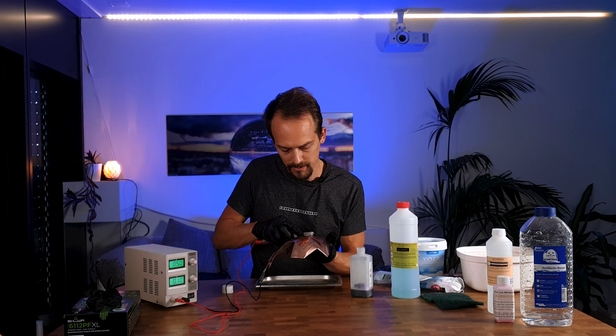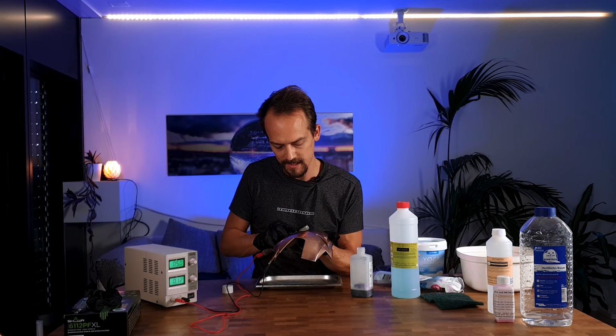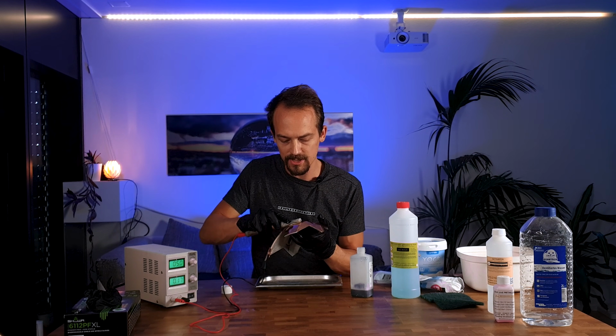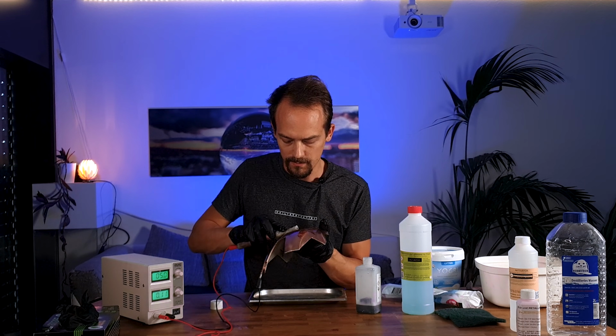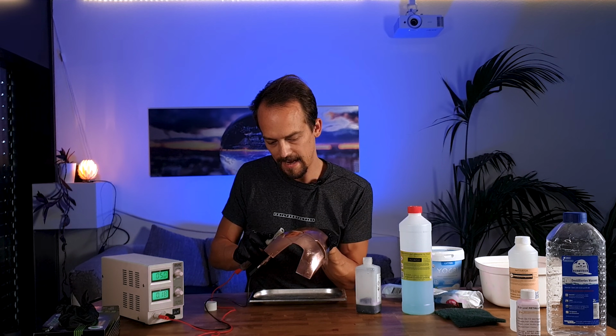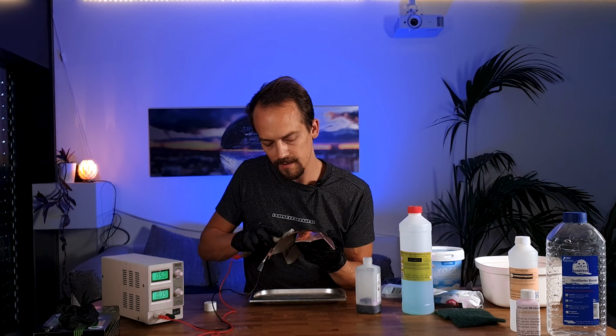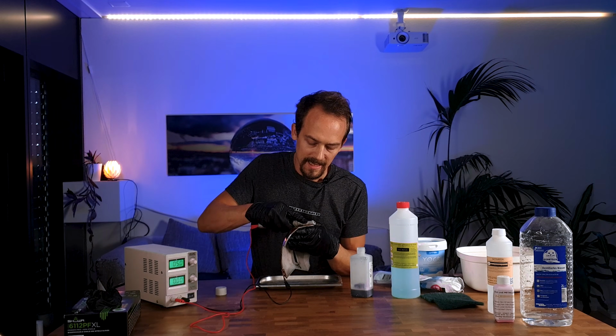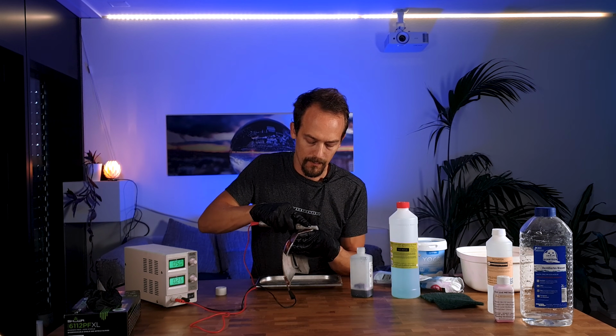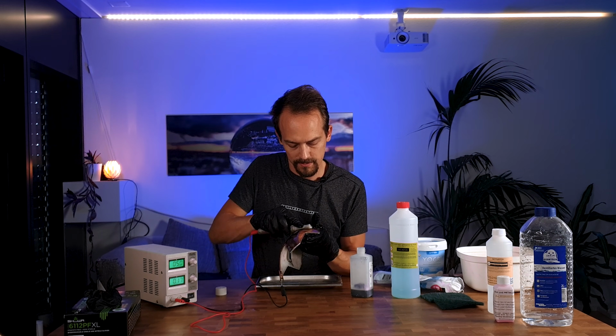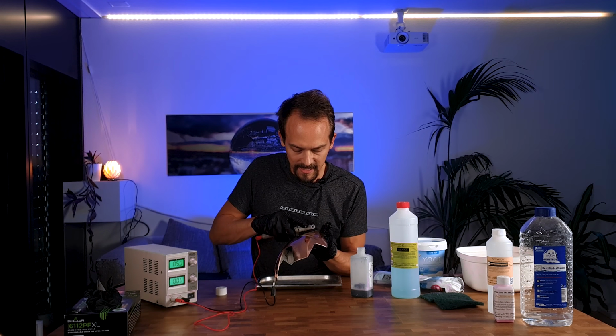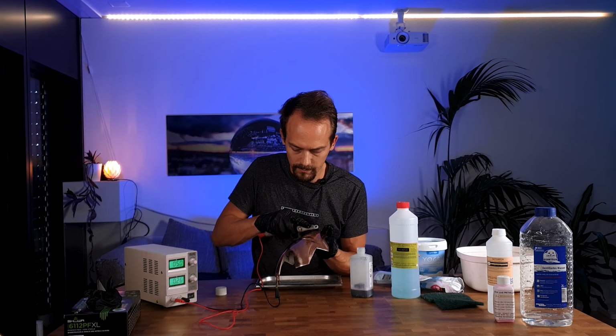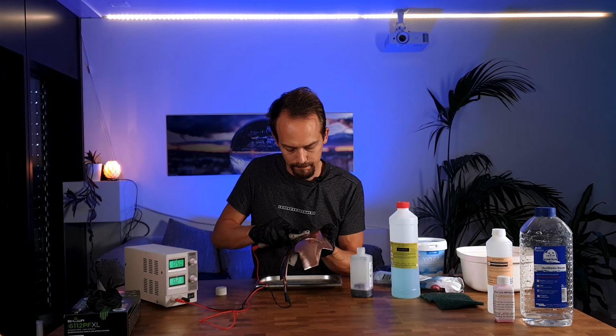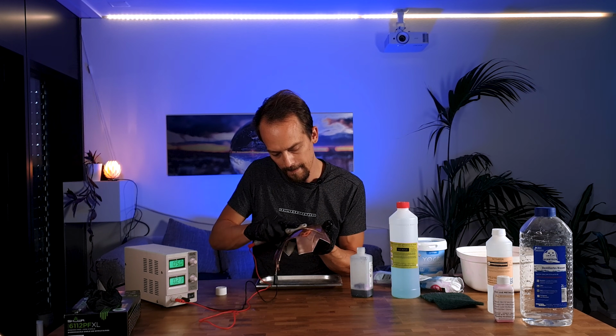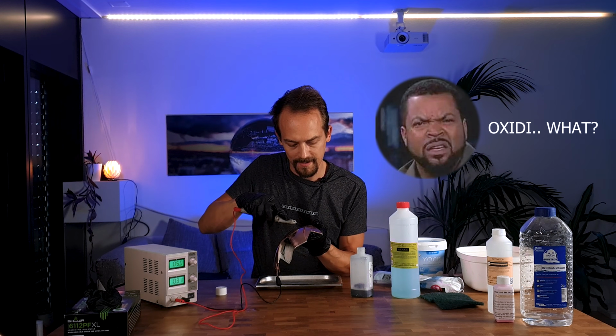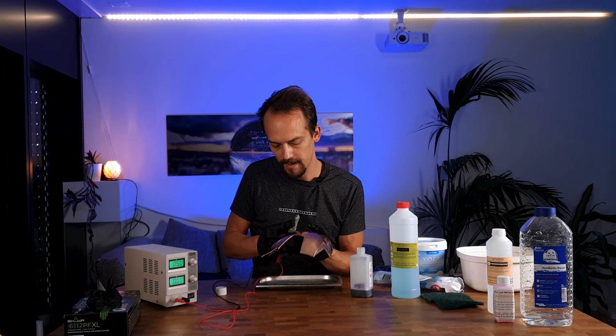And you see the copper getting lighter, like more glossy, losing a little bit of this orange color and going more to rose gold or something like that, because the typical dark orange color of copper is nothing else than an oxide forming on the surface. So we want to strip that oxide, and you see the details I did with roughing up the part will partially disappear or become invisible to the naked eye because the oxidation layer is gone. Go in everywhere you want to plate.